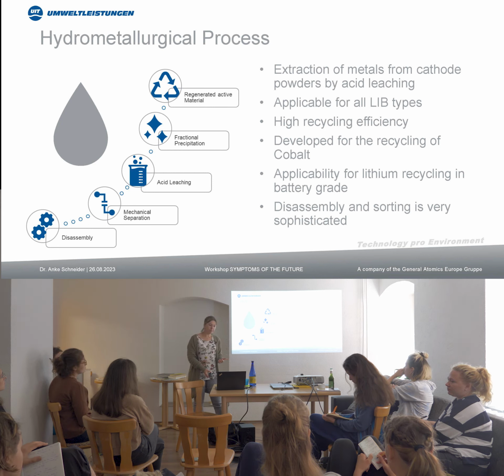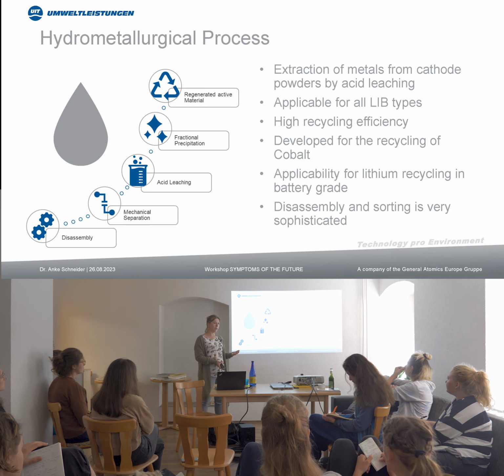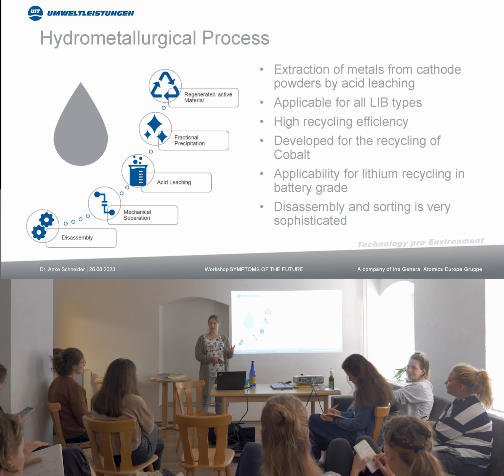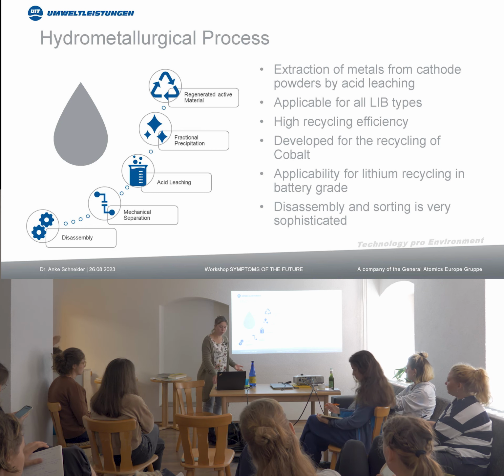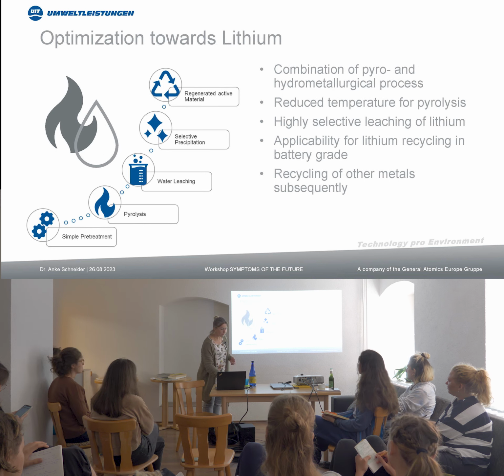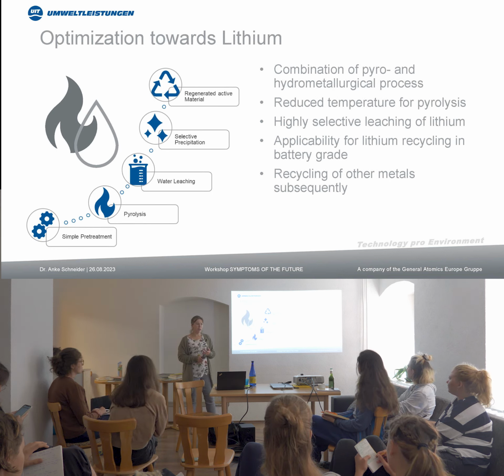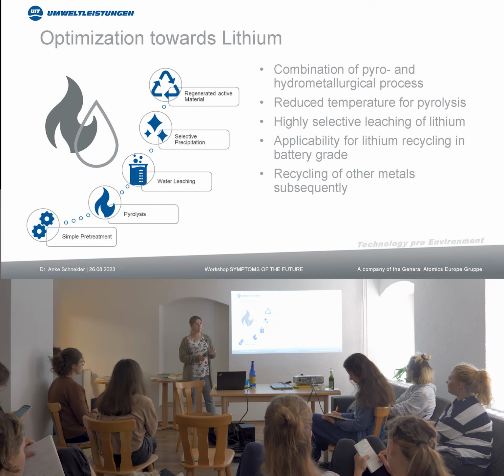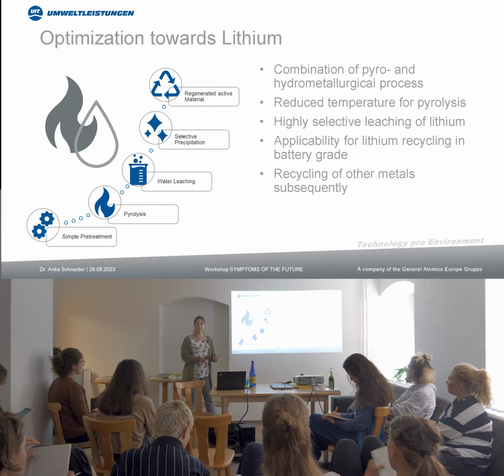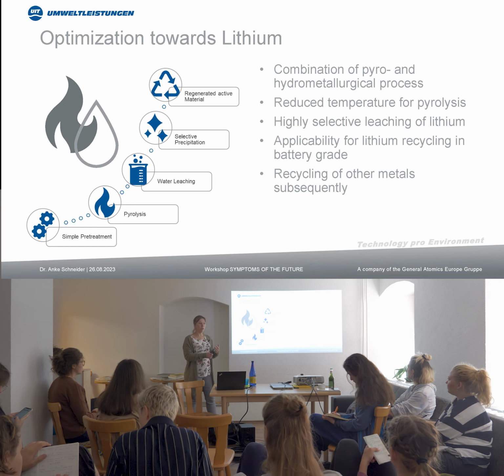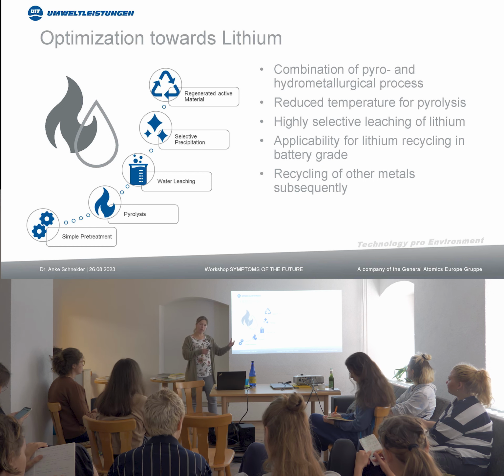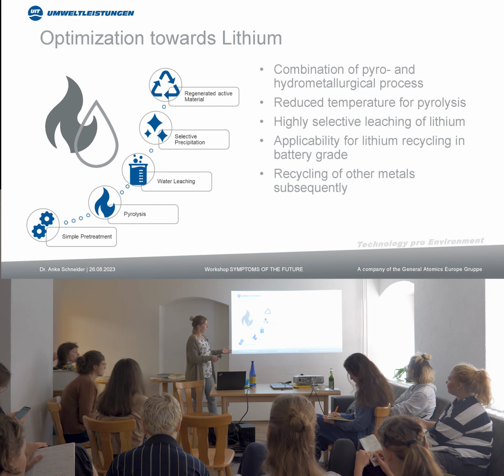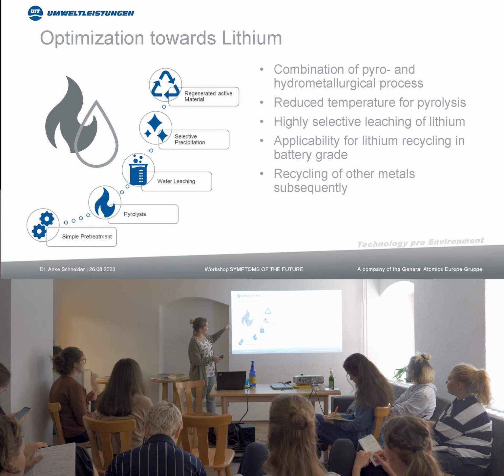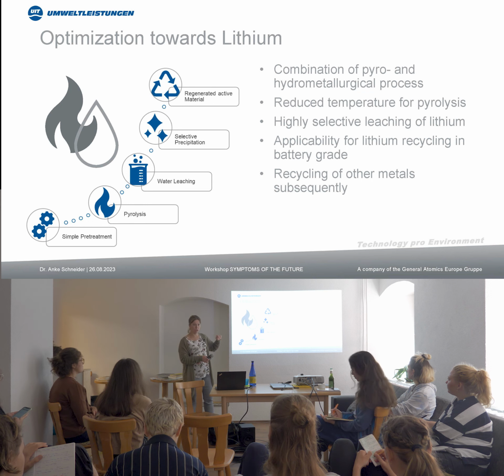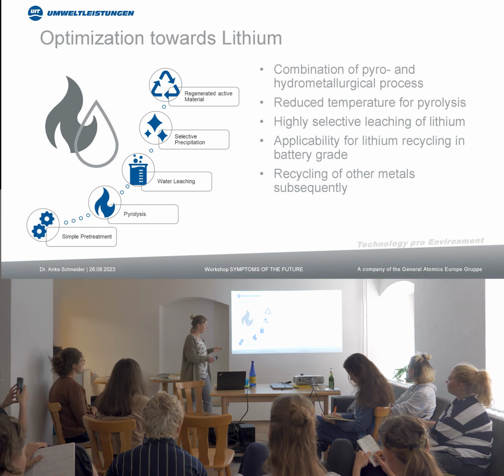And now, during the last years, since 2020, when lithium was determined as a critical raw material for Europe and for our industry, we tried to optimize the processes with regard to lithium. So the optimized process, which is at the moment at a stage where it's not in industry scale, however, already in pilot scale. So the companies are testing it in a bigger scale, but it's not yet industry scale. And this process is a combination of pyro and hydrometallurgical processes and focuses mainly on lithium.